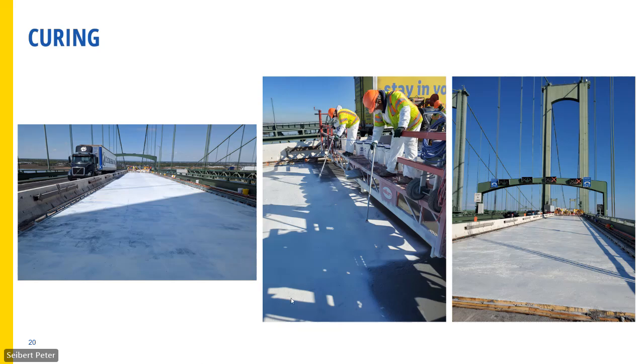We tested a whole bunch of these curing compounds, and we found a nice heavy application of this one here. We're using actually paint sprayers to apply it, and it worked out even better than the plastic without any indents from the plastic.